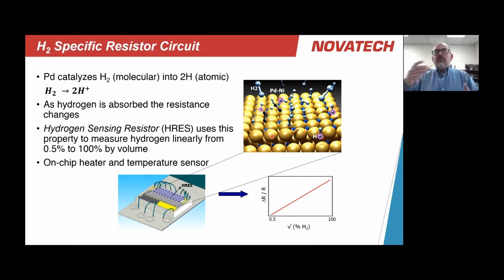And we get a linear response from about 0.5% hydrogen all the way up to 100% by volume. The nice thing is this is a reversible phenomenon, if you will. If I take hydrogen away from the gas, then the hydrogen atoms that are in the matrix will come out of the matrix and form hydrogen molecules again. If I increase the number of hydrogen molecules in the gas, then more of them will go back into the matrix. So it's a reversible reaction, and it basically trends with the conditions of the gas at the